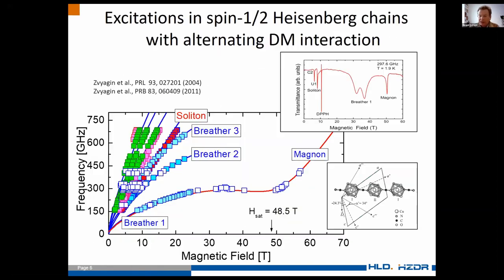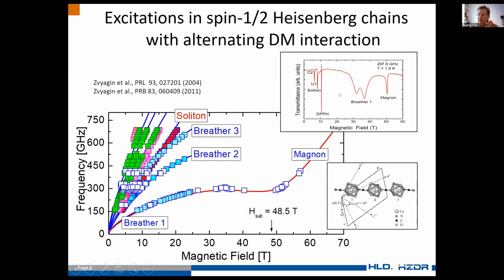So, and this is a typical spectrum at about 300 GHz up to 64 tesla. You can see, so we have soliton, we have breather excitations, and magnon. So the signal to noise is pretty good, assuming that we are working with pulsed field, and the size of the sample is about 2 by 2 millimeter.